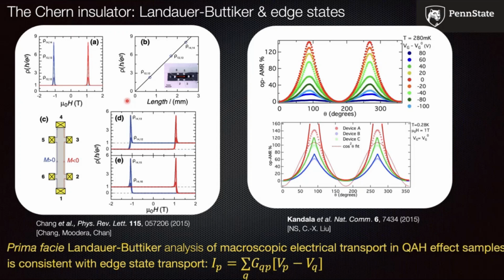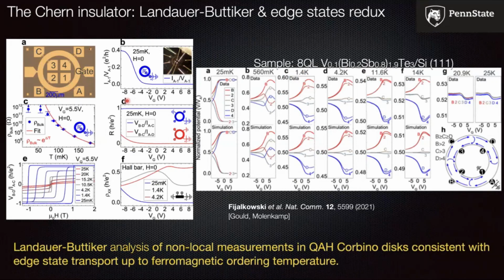As you change the magnetic field angle from out of plane to in plane, and this anisotropic magnetoresistance, if you will, to use a term borrowed from the magnetism spintronics literature, we showed that you could explain this also by using edge states. And then more recently, in Molenkamp's group, they had a very nice paper based on the Corbino geometry, where they again showed that Landauer-Büttiker analysis of non-local measurements in these Corbino geometry disks of quantum anomalous Hall insulators is consistent with edge state transport.